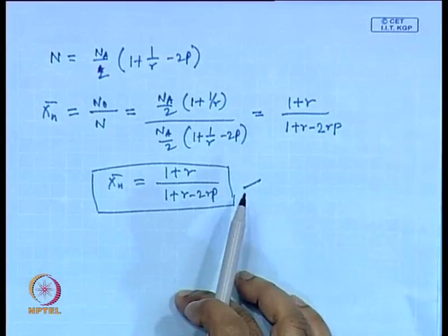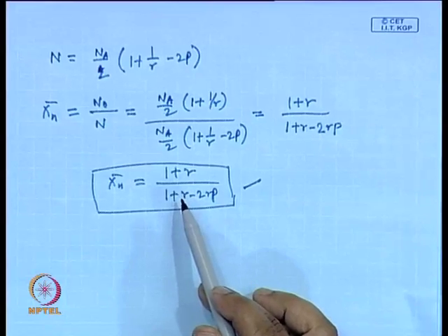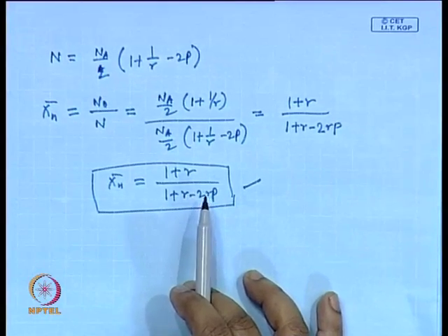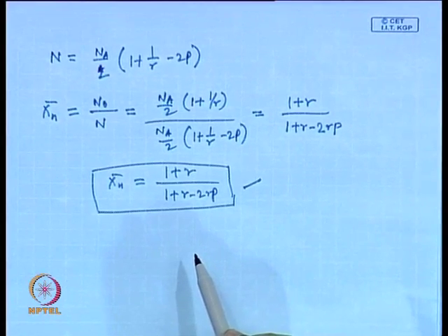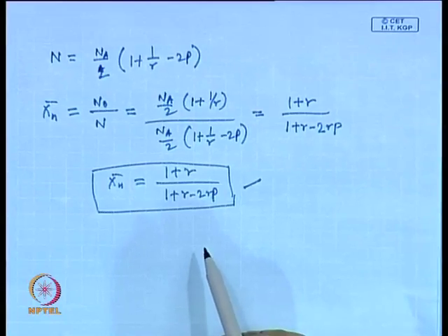You can only know the concentration, or the moles, of each of the monomers and the functional group if they are pure enough. If there are impurities present in your monomers, then you are not sure what the actual mole fraction or moles of the functional groups is, which means you must have very pure monomer in order to get successful step polymers.